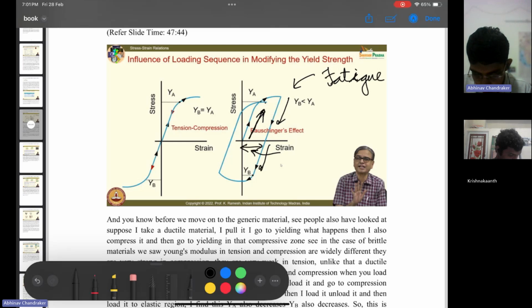So the thing is that what Bauschinger's effect actually tells you is that if you are compressing a material, then it's easier to deform the material by repeated tension and compression rather than just applying tension, due to some internal processes that take place, dislocation-associated processes. You can understand it as the material being much weaker when you apply repeating tension and compression rather than just applying tension. Because of this phenomenon, even if the stress you are applying is much lower than your tensile strength, you can still break a material just by repeatedly loading and unloading it.